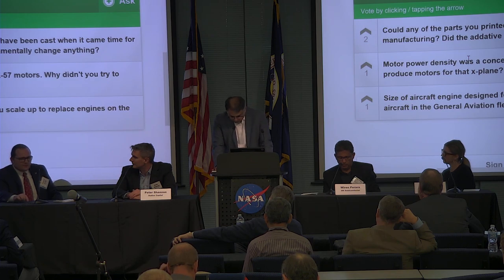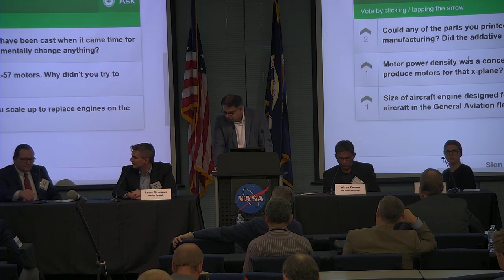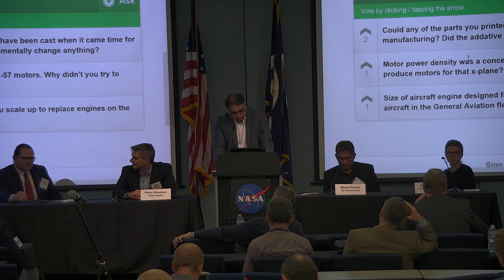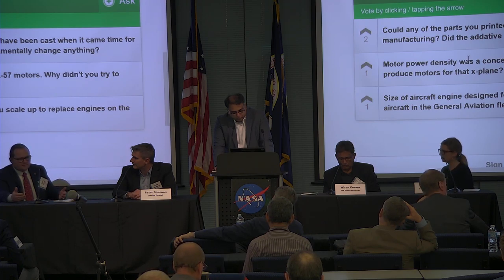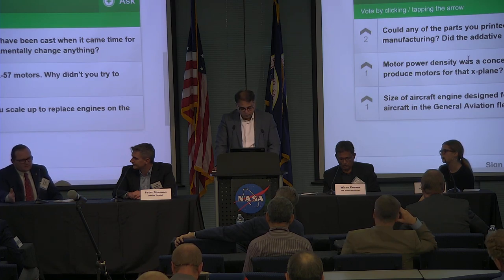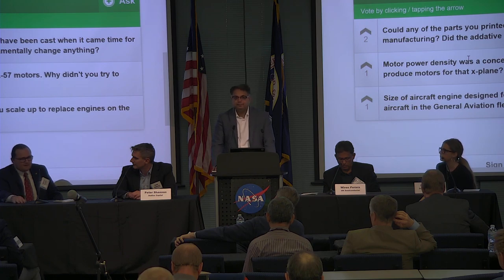The only way I see it helping build more reliable motors is with thermal management components. For example, the heatsink ring taking out more heat, as an example of an additively enabled component, enables a motor to operate at a lower temperature for a given operation scheme. So you're running at 6,000 RPM all the time. Without the heat rejection, you're running at 150 C. With the heat rejection, maybe you're running at 140 C. Well, that 10 C adds up over time with regards to the thermal breakdown of materials. So I would argue that things like that would help with reliability.